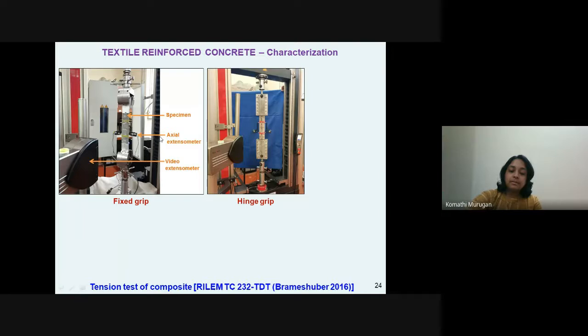There are transducers, such as the contact type axial extensometer as shown here, which is connected to the test panel, and also the non-contact type video extensometer, which captures the displacement in the panel once the test is triggered. So after gripping the panels in the test machine, we apply the tensile load. We apply the tensile load until the concrete cracks, and we stop it when the load reduction is monitored and shown by the system up to 20% of the ultimate load.